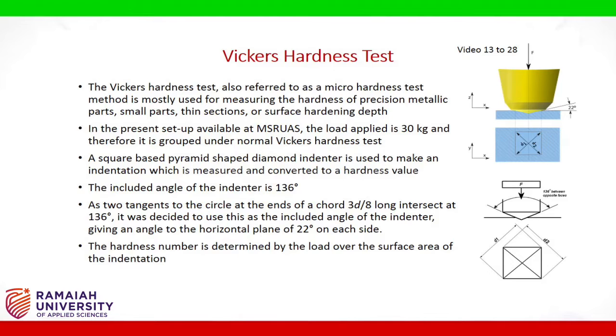In the present setup available at MSRUAS, the load applied is 30 kg and therefore it is grouped under normal Vickers hardness test. A square-based pyramid-shaped diamond indenter is used to make an indentation which is measured and converted to a hardness value. The included angle of the indenter is 136 degrees.